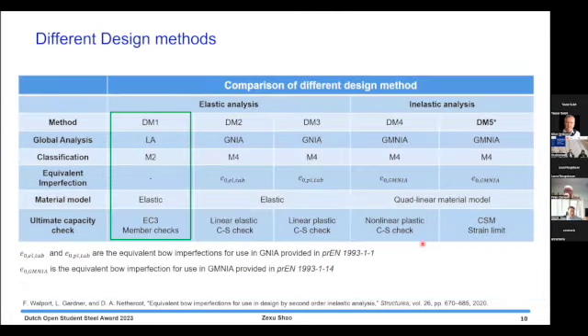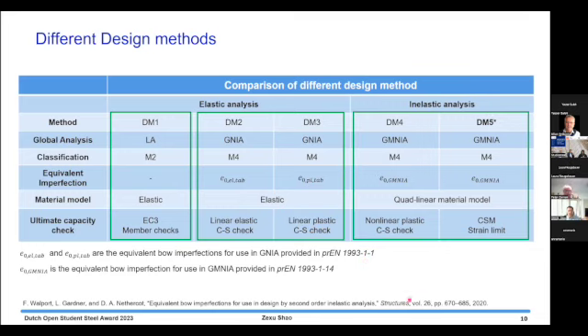We have design method 1 here, which is basically a linear analysis followed by Eurocode 3 member checks. For second order elastic analysis, we have design method 3 and design method 2. They both employ the cross-section check to find the ultimate capacity, but differ in the equivalent bow imperfection adopted and the type of cross-section check. Apart from that, we have design method 4 and design method 5. They are both designed by second order inelastic analysis, employing the same equivalent imperfection for GMNA analysis and the bilinear material model. But design method 4 uses the nonlinear cross-section check, and design method 5 is our proposed design method, of course using the CSM strain limit.